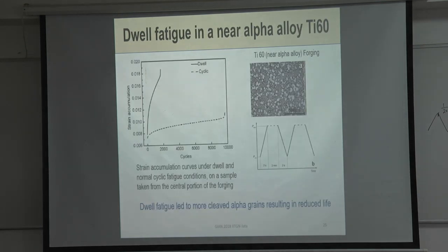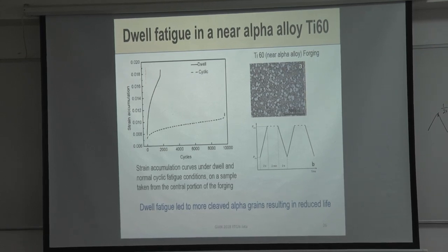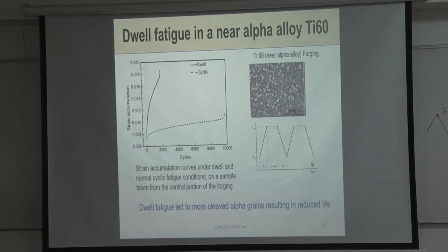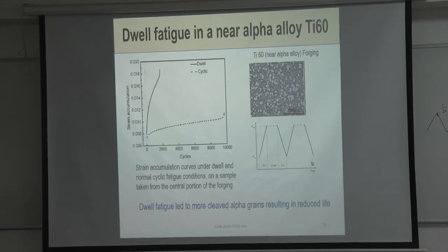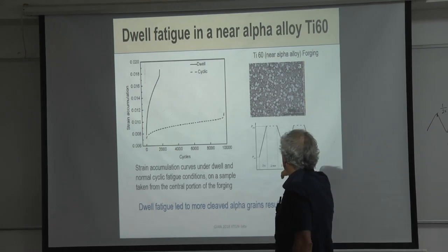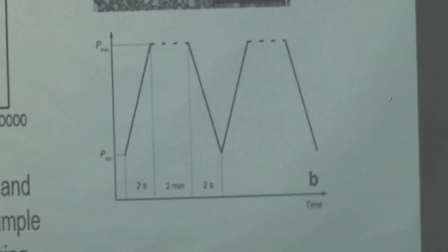Who was asking me about the difference between cyclic and dwell? Here is a graph that shows, on the left side, the graph for pure fatigue. The dotted line is for pure fatigue, and the solid curve is for the dwell fatigue. You can see the differences in the number of cycles to failure. This one is 2 seconds, 2 minutes, 2 seconds: 2 seconds going up, 2 minutes dwell, and 2 seconds coming down. And this is bimodal forging.